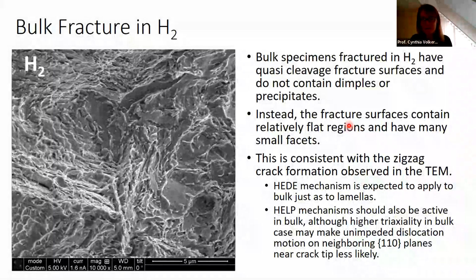So as soon as one has a sharp tip, we think that at the macro scale, one would expect flatter fracture surfaces, and these 100 facets that we find at the submicron scale are, we believe, consistent with the type of observations one sees, for instance, here and on surfaces like this here, where these facets, we don't know the orientations of these facets, but we believe that these facets we see in the TEM could have the same mechanisms that are causing these apparently faceted surfaces here at the fracture surface for the hydrogen case. So we believe that what we're observing in the TEM gives us some clues about how we get these quasi-cleavage surfaces in the bulk case.